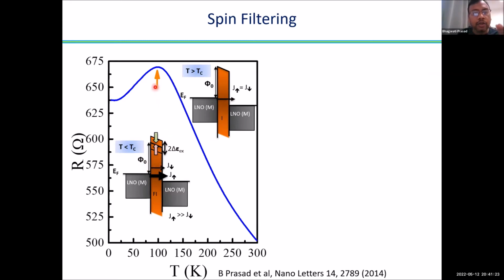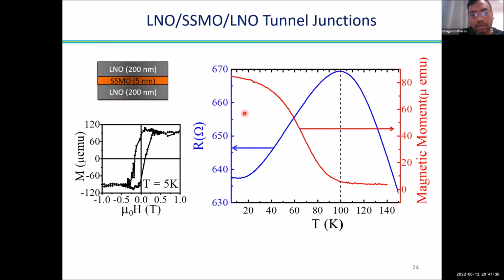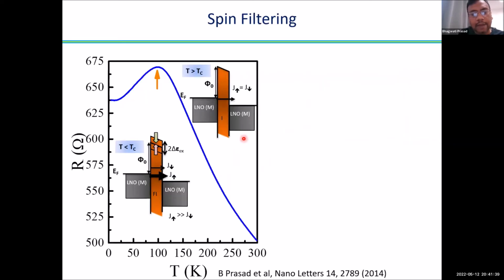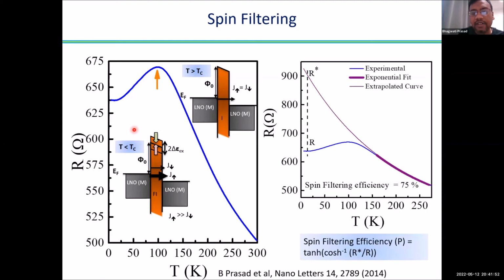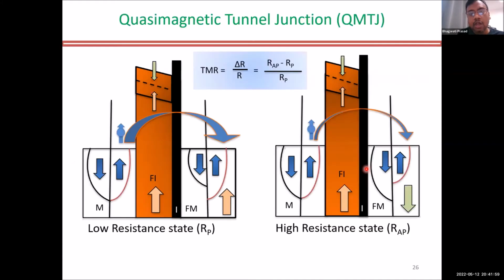If you reduce the temperature further down, this splitting will increase more and more, and you see more and more of the up-spin electrons will be here. When you hit here, you basically saturate. You see here, this is some sort of saturation. There is no further splitting, and that's why the resistance will become flat here. So this lowering of the resistance at low temperature below the TC provides the evidence of spin filtering. We fit this data with some sort of model, and from that we get that the spin filtering efficiency in our device is around 75%. So that's one way.